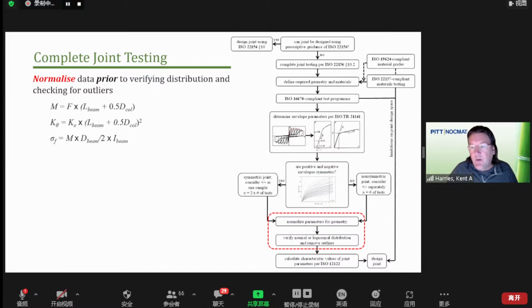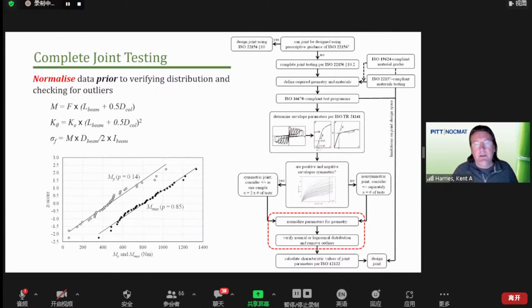And with that data now, we want to determine: does this data fit a normal or a log normal distribution? This is an important step, and I've seen it left out in some types of studies. When we go to determine characteristic values using conventional means, ISO 12122 or ASTM methods or what have you, there is a presupposition that we have a normal or a log normal distribution. And if we don't, the calculations of characteristic values using these tabulated values or very simple equations is incorrect.